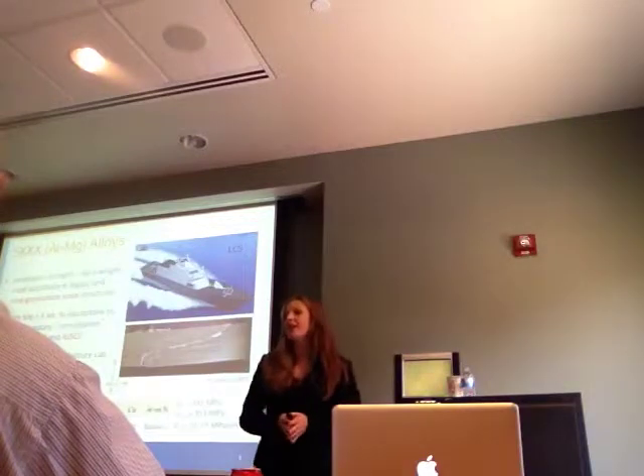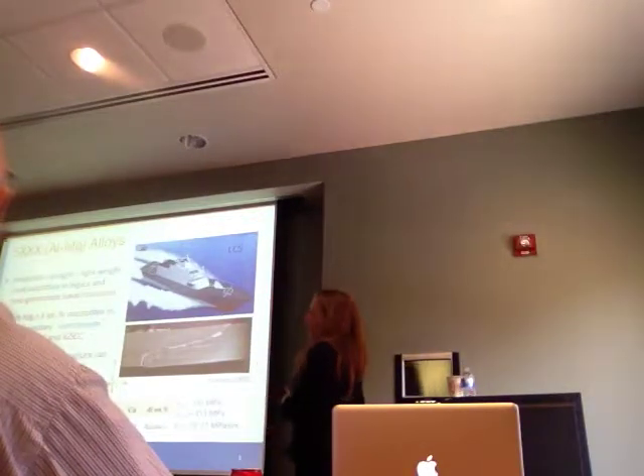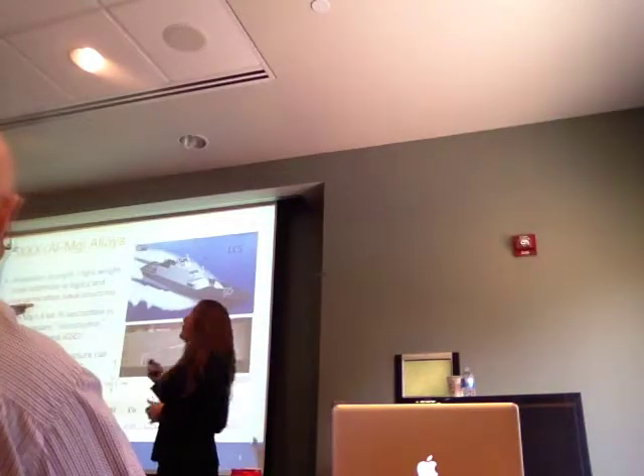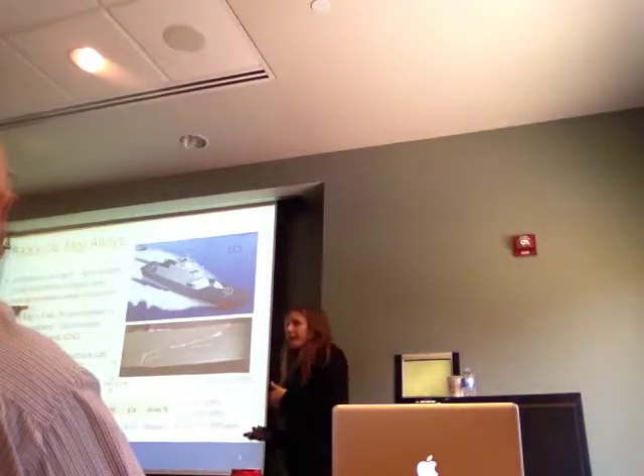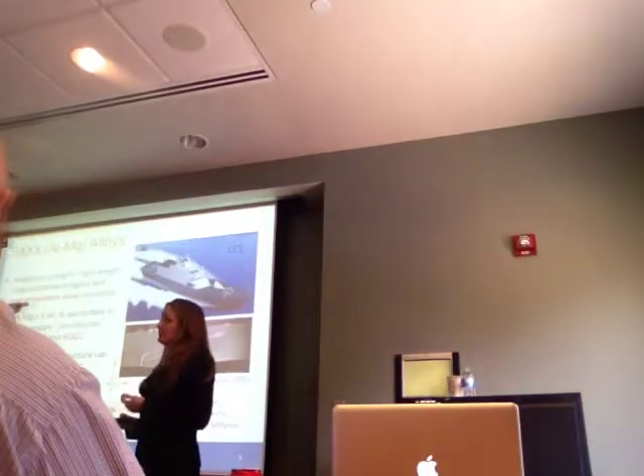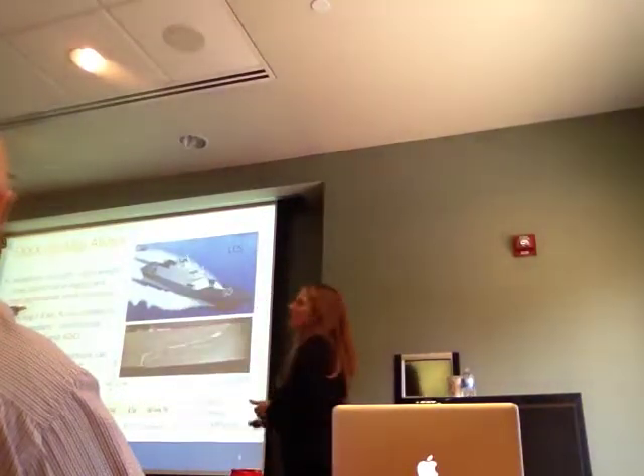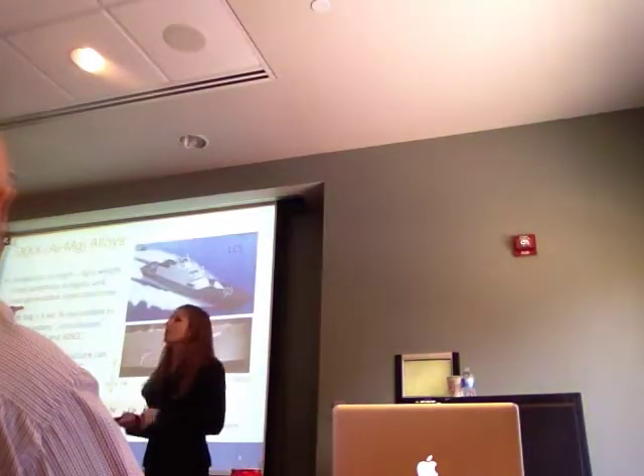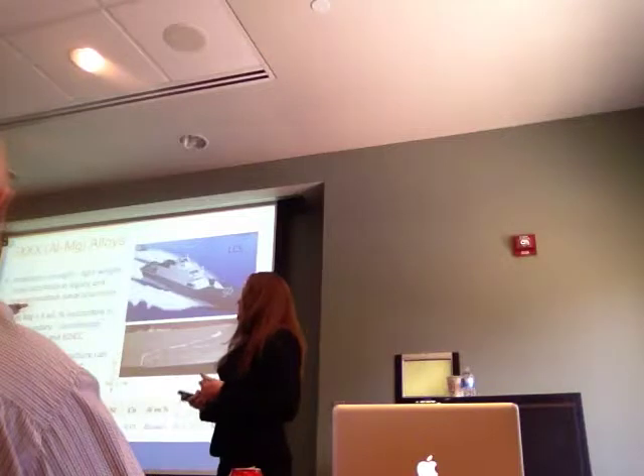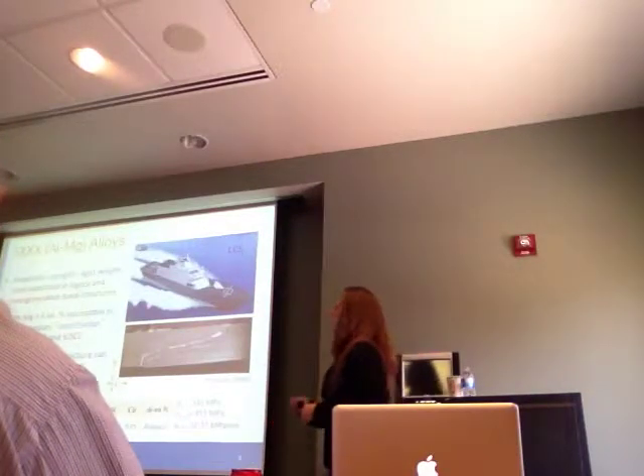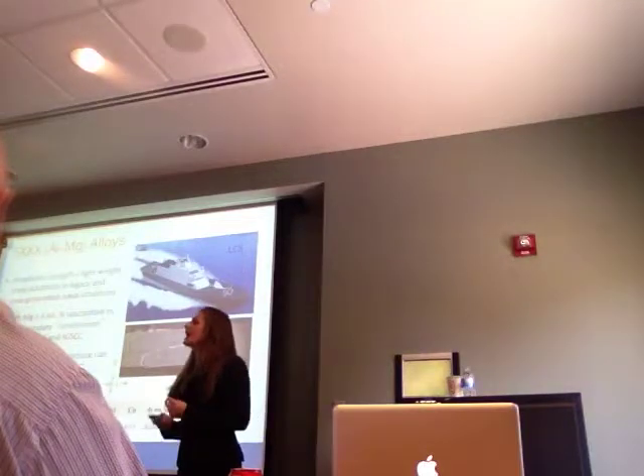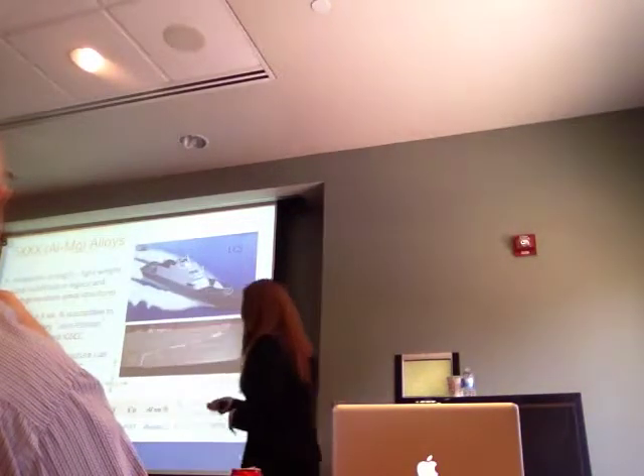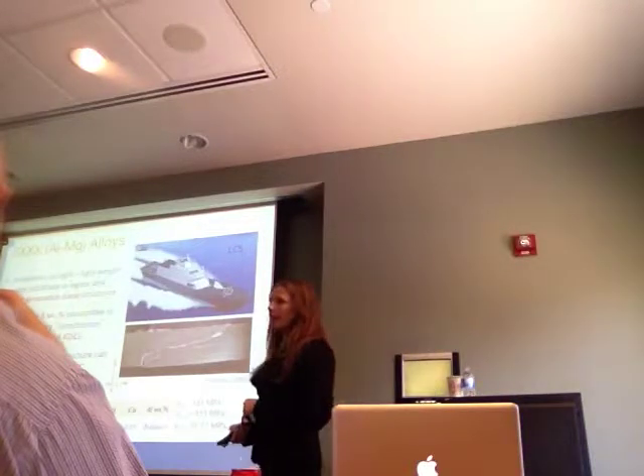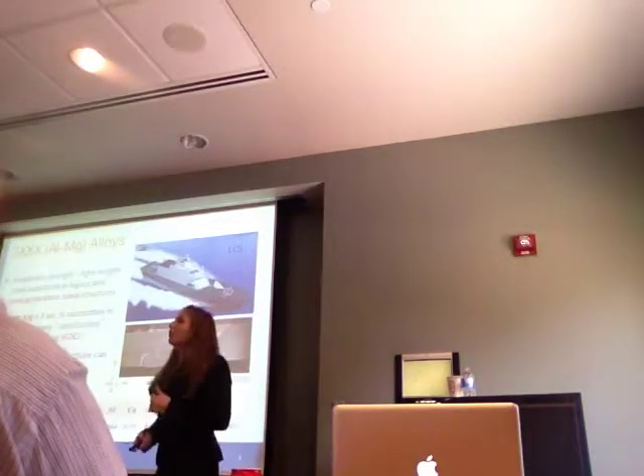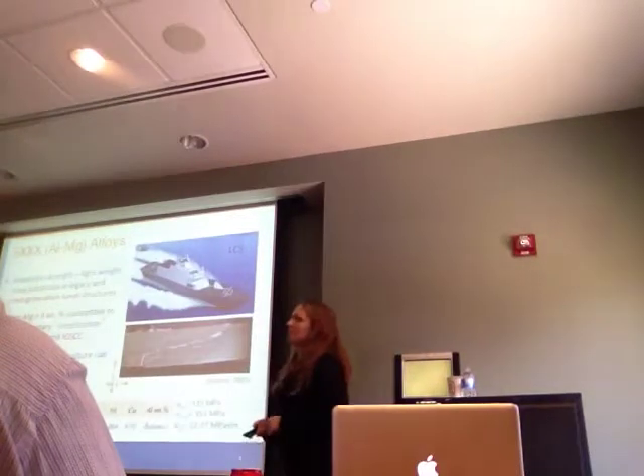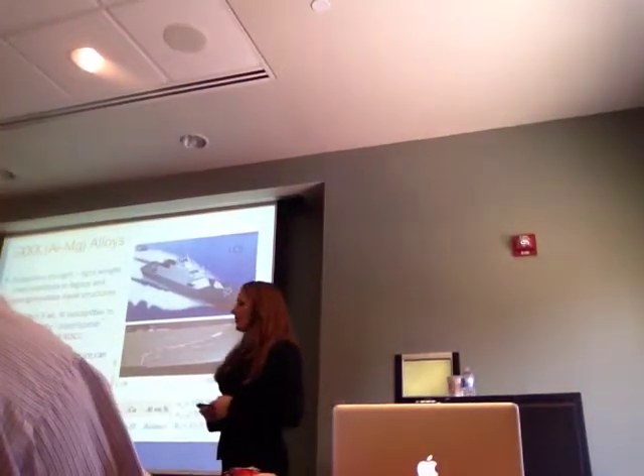All right, to start off, 5000 series alloys are aluminum magnesium alloys. They're solid solution strengthened by their magnesium content, which gives them moderate strength, lightweight, and a great substitute for steel. So they've been used in a lot of the next generation naval structures. The problem is when you have more than 3 weight % mag in the alloy, you become susceptible to sensitization, which leads to intergranular corrosion and intergranular stress corrosion cracking. Now, as you can see, our alloy down here, 5083, H131, has 4.4 weight % mag. So we are definitely susceptible to intergranular corrosion and intergranular stress corrosion cracking.